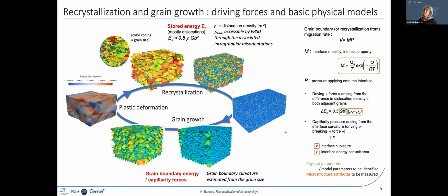So these phenomena are basically of two types. I mean by this that if you take a polycrystal and start deforming it, of course, energy will be stored in the microstructure in the form of defects, mostly dislocations. And once you reach a critical amount of stored energy or dislocation density, then you would see new grains forming and developing. This is the so-called recrystallization phenomenon, which is driven by the consumption of the stored energy. So again, by stored energy, I mean mostly the contribution of the stored dislocations.